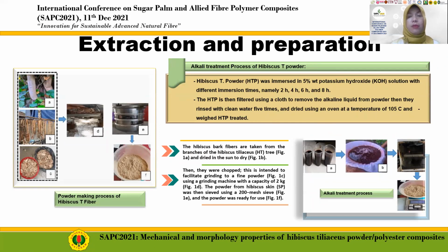The alkali treatment process of hibiscus powder begins with the powder immersed in a 5% potassium hydroxide solution with different immersion times, namely 2 hours, 4 hours, 6 hours, and 8 hours. Then the powder is filtered using a cloth to remove the alkali liquid, rinsed with clean water 5 times, and dried in an oven at a temperature of 105 Celsius, and then we have the treated powder.